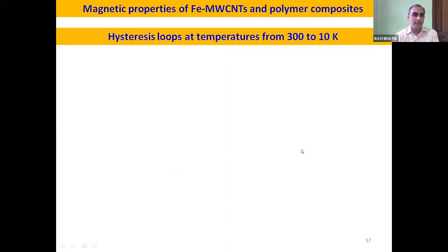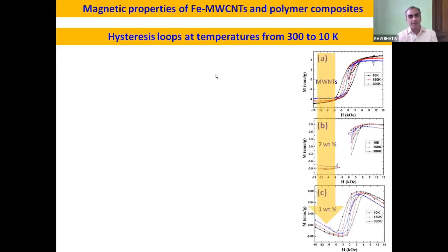So hysteresis loops were measured. One can say only hysteresis loops. Why? Because the size of the iron nanoparticle in terms of a nanoroll is big enough to look for its superparamagnetic properties by ZFC or FC measurements. So we had to go for only MH loop measurements.